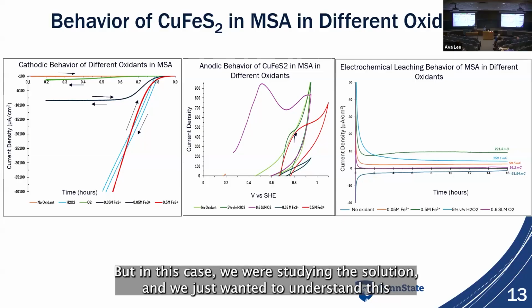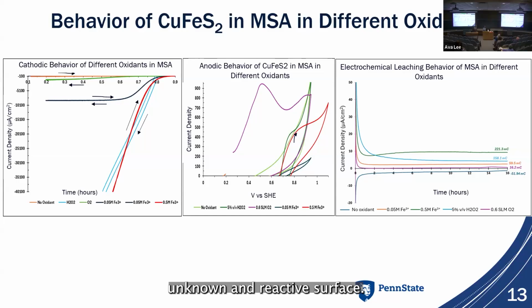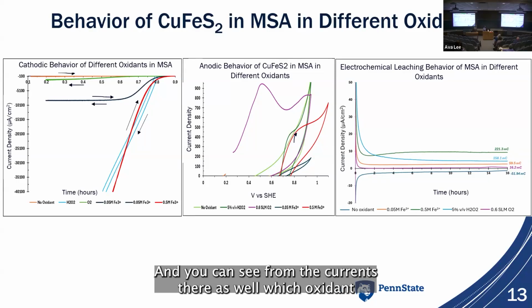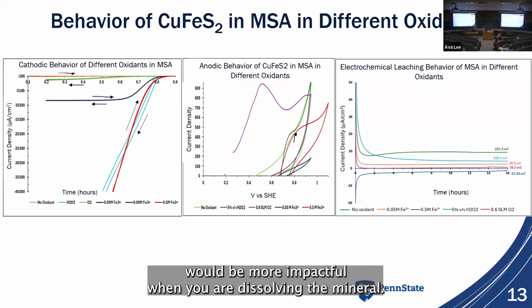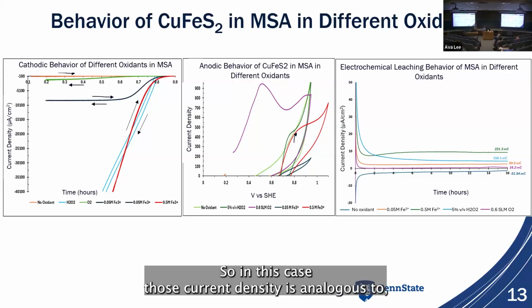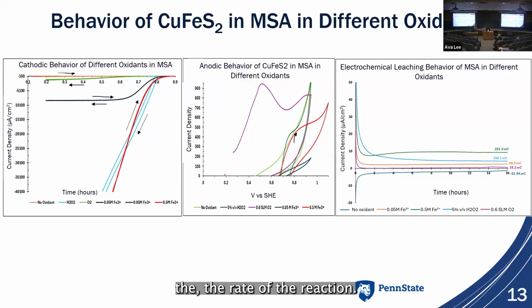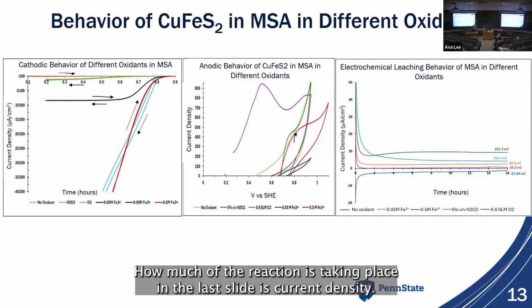But in this case, we were studying the solution, and we just wanted to understand this on a non-reactive surface. We look at this as well on the mineral surface, and you can see from the currents there which oxidant would be more impactful when you are dissolving the mineral. So in this case, those current densities are analogous to the rate of the reaction, how much of the reaction is taking place. In the last slide, there is current density.